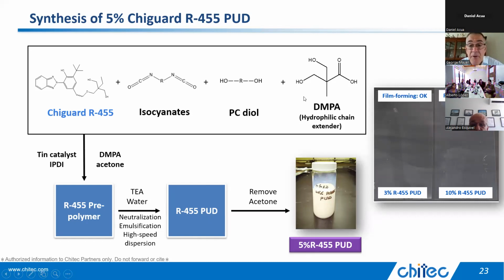And then typically there'll be a co-solvent in here. Acetone is very volatile. Methylethyl ketone is sometimes used, and you just strip that off. And then you have a polymer now, a urethane polymer that's dispersed in water that has your UV absorber built right into it. And you can see here, they look fine. Actually, the real panels looked even better than this picture, but it disperses in and forms a really good film.